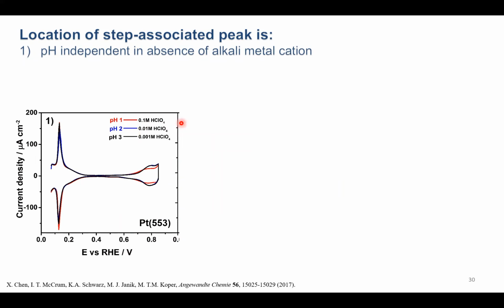So how do you do this? You take a strong acid and you dilute it. And what she finds is when you vary the pH without adding an alkali metal cation, the peak does not shift. The step-associated peak remains at the same potential. And so there's actually 3 CVs here that all overlap on top of one another. And so this would seem to support that if we don't have the cation in the electrolyte, we don't see the peak shift. And this also suggests that since we're changing pH, this means we are changing the electric field across the surface. And this means adsorption in this peak shows no electric field dependence, at least from pH 1 to 3, at least over the small pH range.